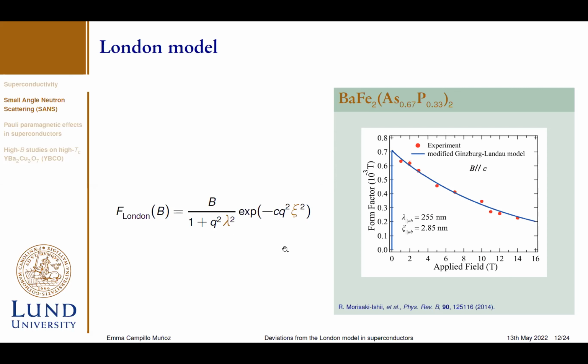As we can see, this London behavior, or this decreasing behavior of the form factor with increasing field, can also be found in unconventional superconductors, such as the barium-based superconductor we are showing on the slide. The other important feature is that using this London expression, we can calculate the London penetration depth and the coherence length for a specific superconductor. This is the ideal case.